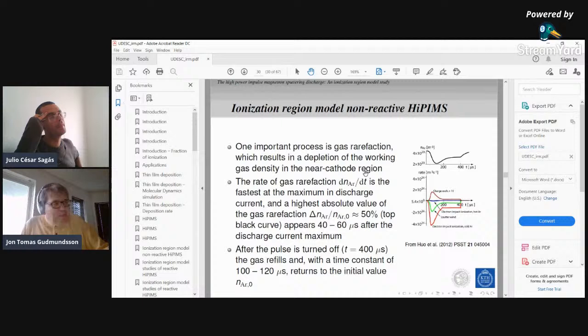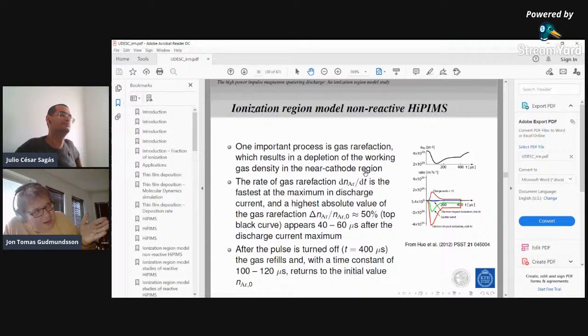Yeah, so the bipolar HiPIMS is a regular HiPIMS where another pulse follows the main pulse, and this second pulse is positive. So what it basically does, it increases the plasma potential in the ionization region, and that means it pushes out the ions towards the substrate. And it seems they have been able to demonstrate experimentally that by the amplitude of this positive voltage, you can more or less control the ion energy of the ions as they hit the substrate. So this can have some benefits and increases the controllability.